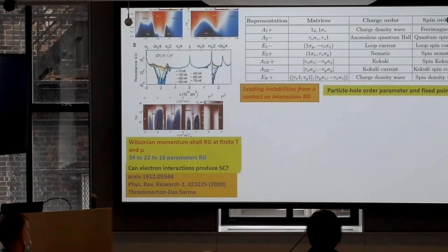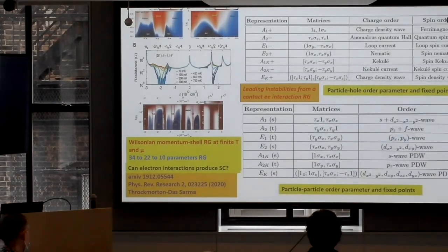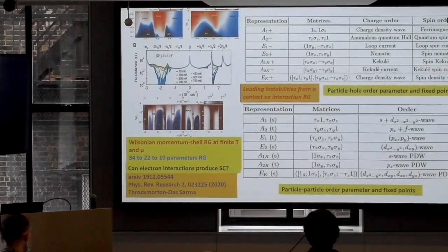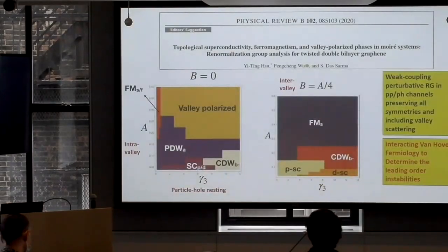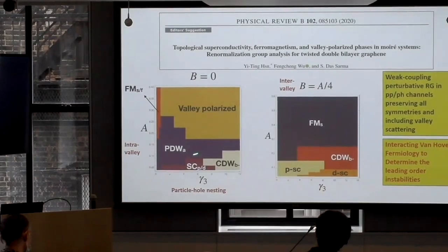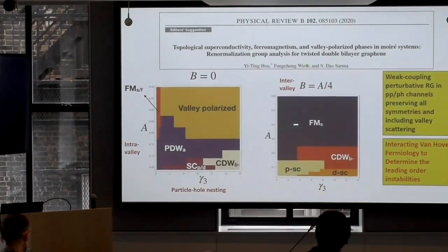There are many, many phases, and all of those phases are coming from electron-electron interaction, okay? And the superconductivity is invariably some high orbital superconductivity, which is what we expect. I'm not going to talk about this. This is just to say that it's not like we ignored electron-electron interaction completely. We did the calculation that everybody else does, in our own language, and we found topological superconductivity. We found all kinds of density waves and the superconductivity P and D. But I do not think that these findings of ours, and there are many, many papers like this in the literature, they're all very nice theoretical papers.